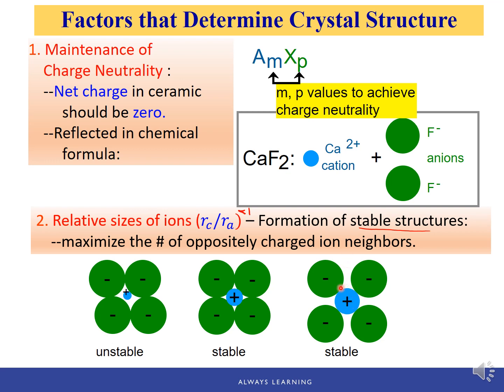The radius of this cation is slightly bigger than the size of the hole, or the interstitial site, so it pushes out the close-packed anions a little bit. So the anions are not in touch anymore. But since the cation is in touch with all the oppositely charged ion neighbors, this is also a stable structure. In other words, the atoms or ions we put into the interstitial sites, or the voids, should be at least the same size as or bigger than the interstitial site. We cannot put a smaller cation into the interstitial site. That will form an unstable crystal structure.